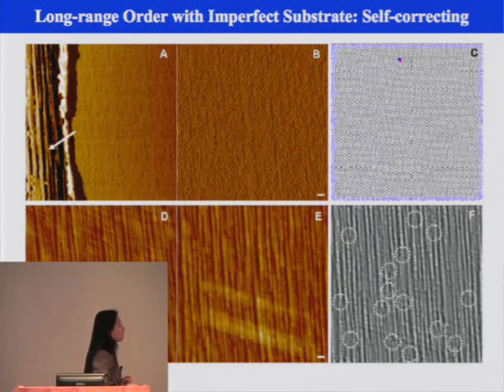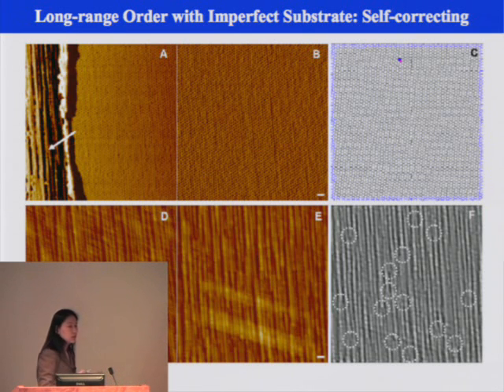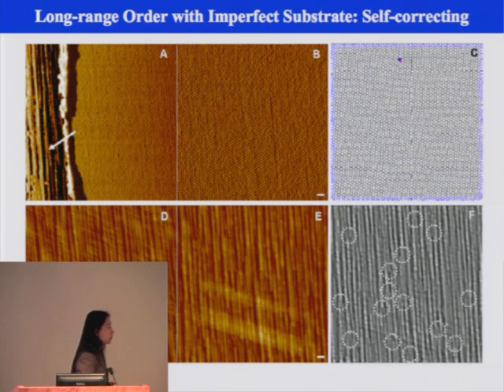You can also look at the AFM image on top, to look at the correlation between the defect in your underlying substrate versus the top surface ordering of the block polymer.